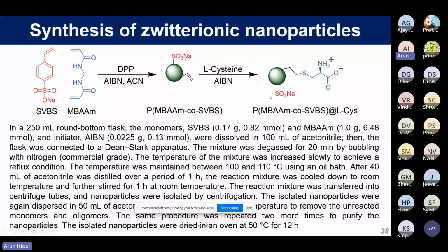The monomer here is different. One of them, bisacrylamide, is the same. Another, instead of the sulfobutane, we have used this SVBS monomer. Once the DPP, distillation precipitation polymerization, was done under the same conditions as the previous, the formed zwitterionic particle was reacted with L-cysteine, one of the amino acids, which we commercially procured. You can see the zwitterionic polymer nanoparticles chemically bound to the L-cysteine amino acid. So this particular additive has further improved the performance of this material.